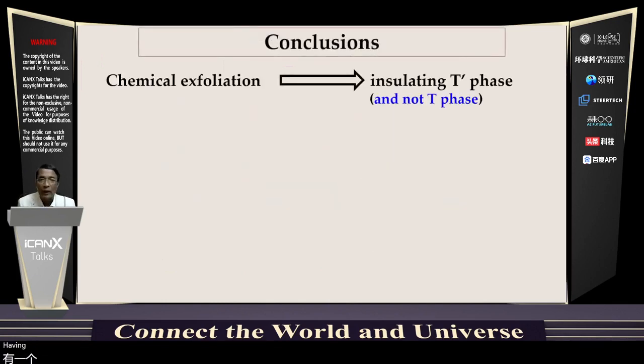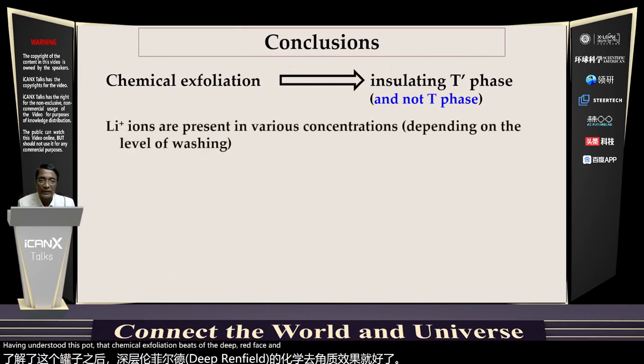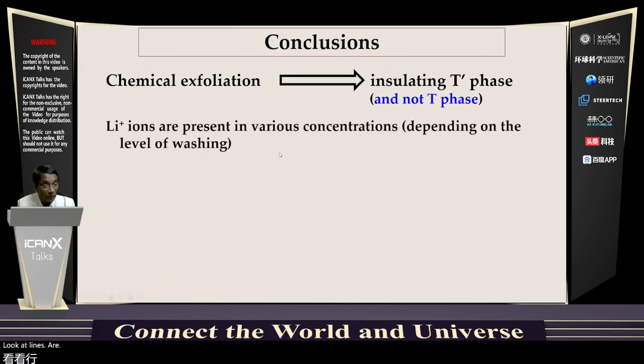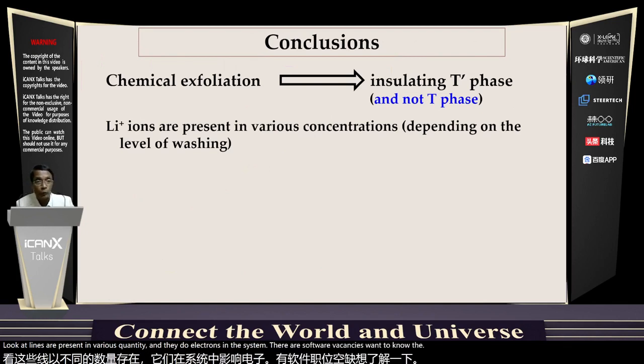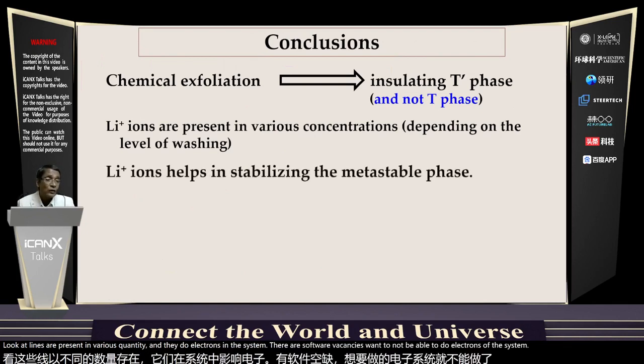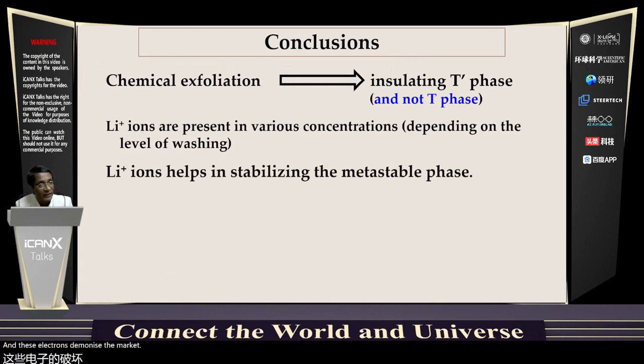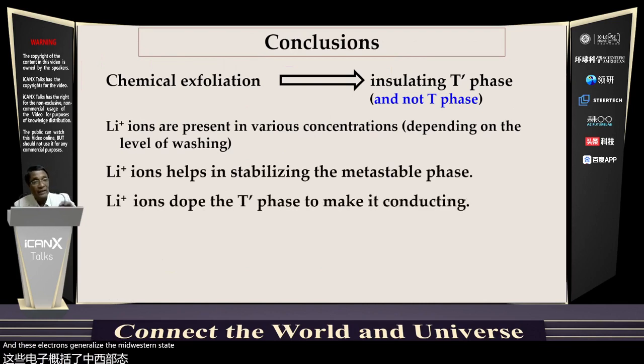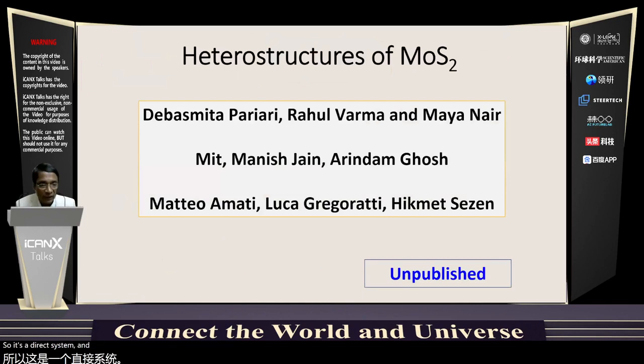Having understood this part, that chemical exfoliation leads to the T prime phase and not T phase: lithium ions are present in various quantity and they dope electrons in the system. There are sulfur vacancies also known. They also dope electrons in the system. And these doped electrons stabilize the metastable state, and make the T prime phase appear conductive. So it's a doped system, and that's why it's conductive.